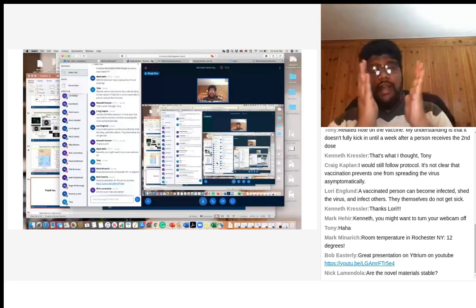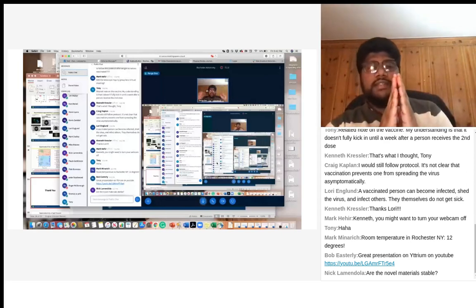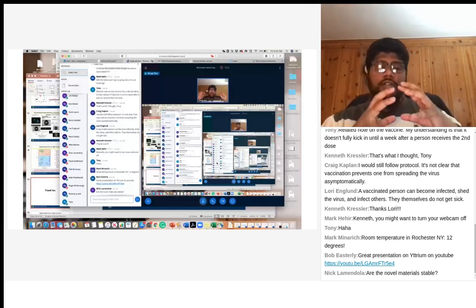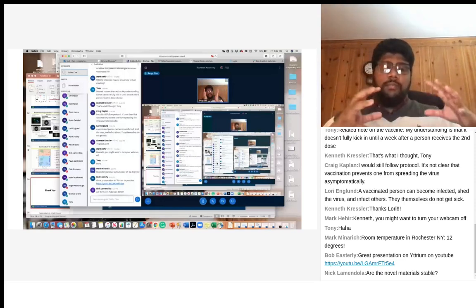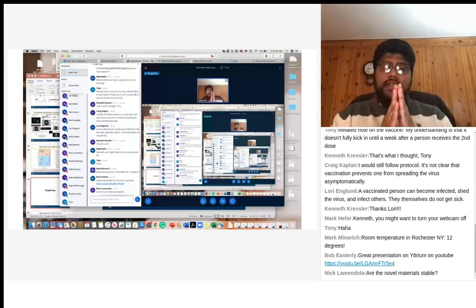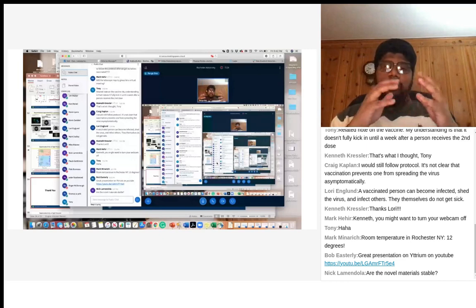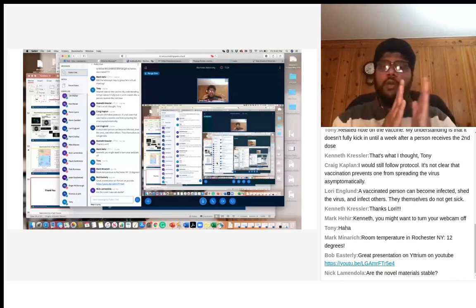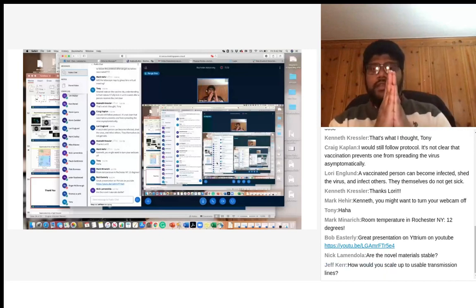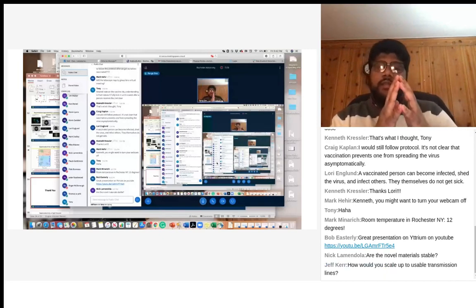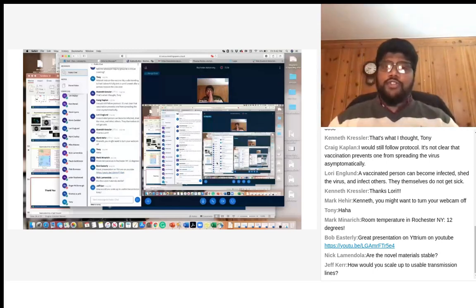Also, since these are really high pressures, when you release the pressure, even though you're releasing your mechanical press, they don't really go back in the same way. There's something called cold welding. The metal gasket and the diamond sort of weld together. So when you try to release it, it tends to rip the diamond and break the whole diamond, and then you lose your sample.